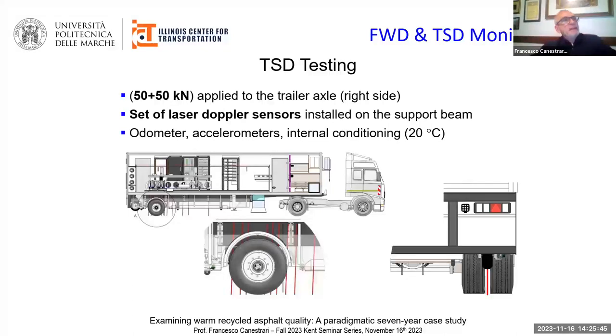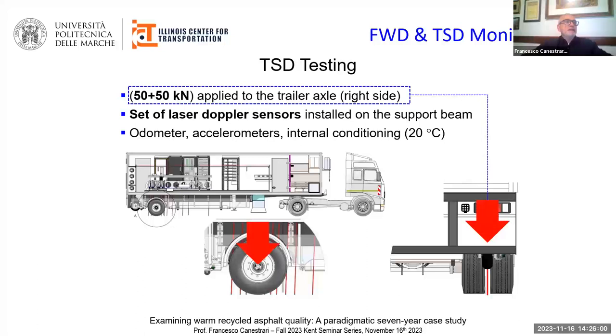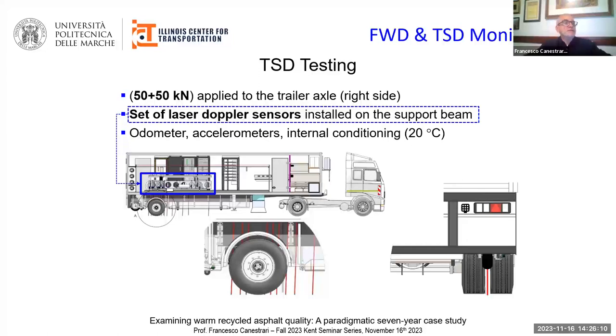The pavement bearing capacity has also been monitored by means of a traffic speed deflectometer since 2022. Only preliminary results are available at the moment, of course, and the traffic speed deflectometer allows the measure of the surface deflections induced by a 100 kN trailer axle, thanks to a set of laser Doppler sensors installed on the support beam.